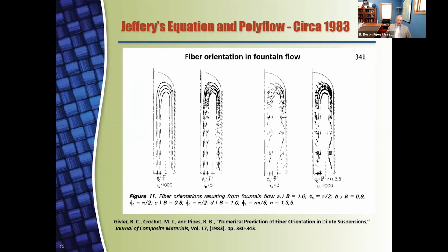We looked at single fibers in multiple positions in this flow, and you can see as the flow turns back on itself, for long aspect ratio fibers, that is to say 1,000, and with an initial orientation of pi/2, the fibers really don't change orientation state very much to the left. Now, if you shorten that fiber substantially, again, you're using the classical interaction here in Jeffrey's equation for single fibers that are not interacting with other fibers. Nonetheless, what you see is that the fiber begins to rotate. It both turns orientation, but it also rotates and turns. As you make the aspect ratio of the fiber shorter, you see this is enhanced significantly.